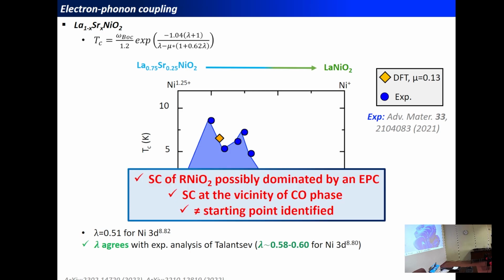And therefore, we conclude that superconductivity in these nickelates could possibly be dominated by an electron-phonon coupling phenomenon, which is compatible with what has also been suggested recently in the literature. That superconductivity in this case is in the vicinity of a charge-ordered phase, but only if we start from the left side of the phase diagram instead of starting from the infinite-layer phase.